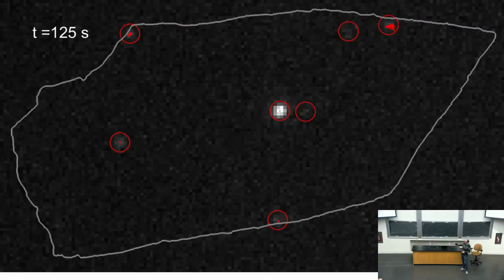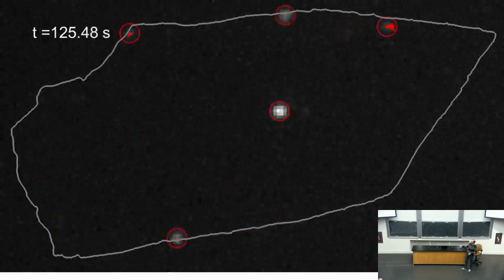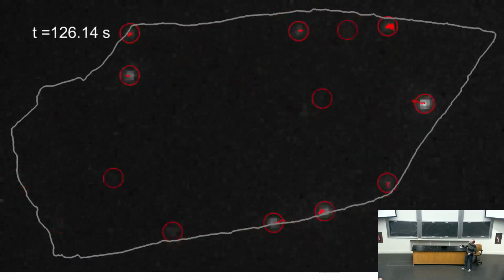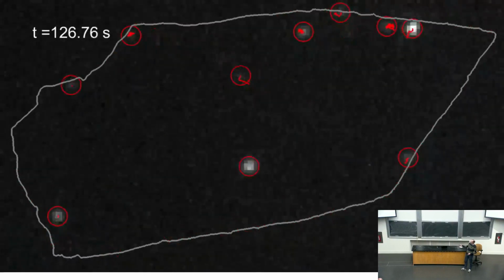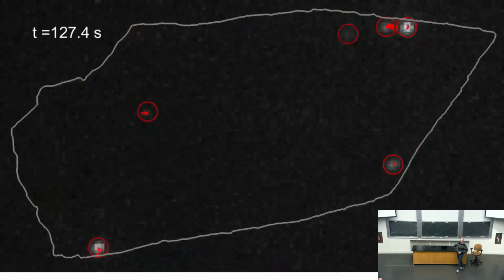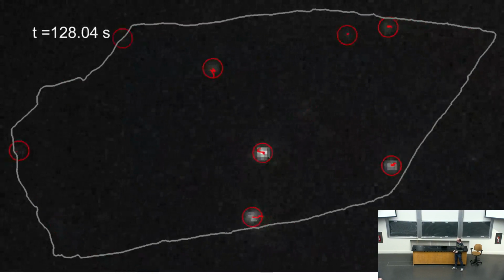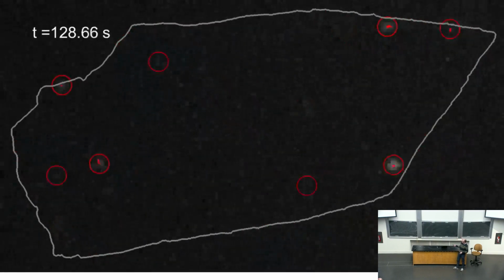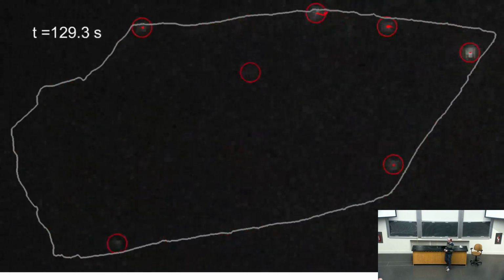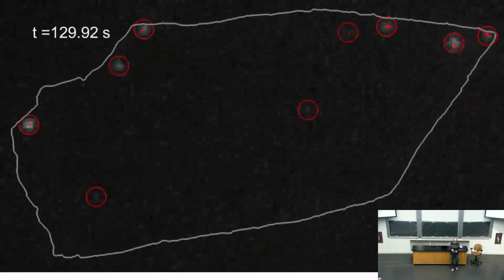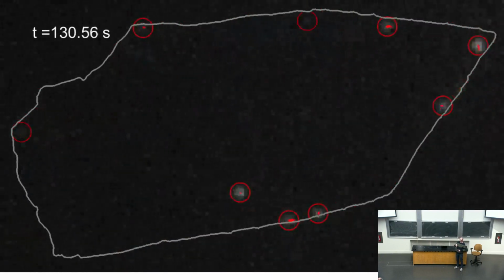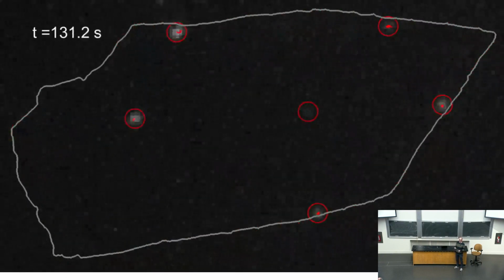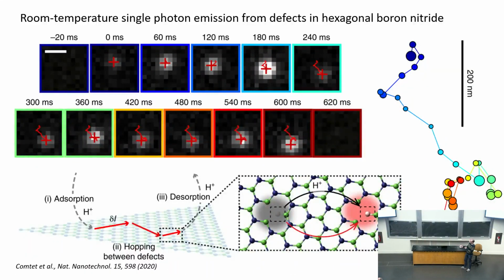And what you'll see is, so this is super resolution images as a function of time. And wherever something bright lights up, it's an emitter being active. And with time, they'll change to dark. So what they see is that at different times you will have emitters lighting up. But then as they light up, they also start to move a little bit where they are, or around where they are. So what they've been suggesting is going on here is that actually some of these emitters are made active by surface protons or excess protons in the fluid, attaching for a certain amount of time to the defect, making it bright and then leaving again.